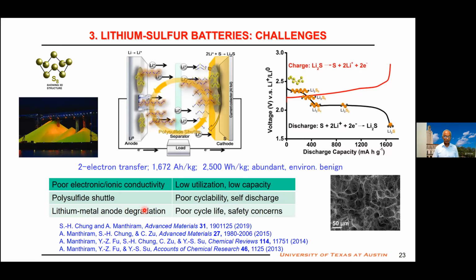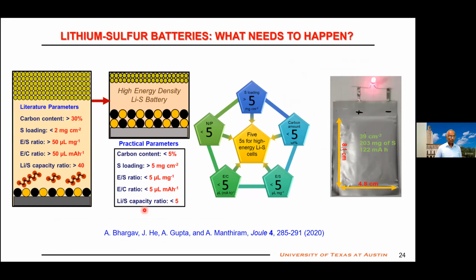But one thing is, a lot of work is focused on publishing, adding carbon to overcome electronic conductivity. A lot of liquid to overcome ionic conductivity, because if we add too much liquid electrolyte, the dissolved polysulfide can diffuse easily, so you can overcome the lithium ion diffusivity in the electrode. But that will pathetically lower the energy density, because you have unwanted carbon, unwanted too much electrolyte. So our goal is here.